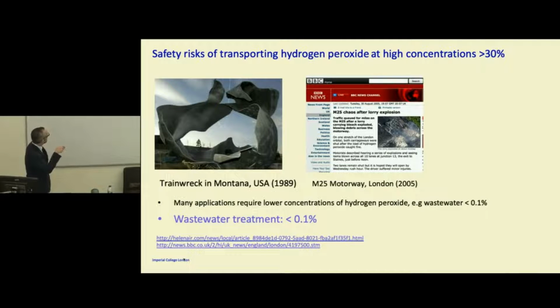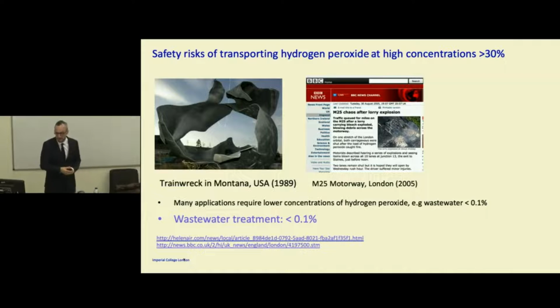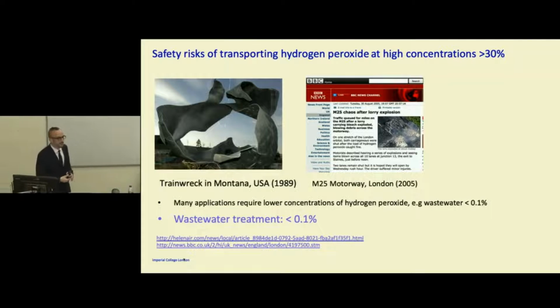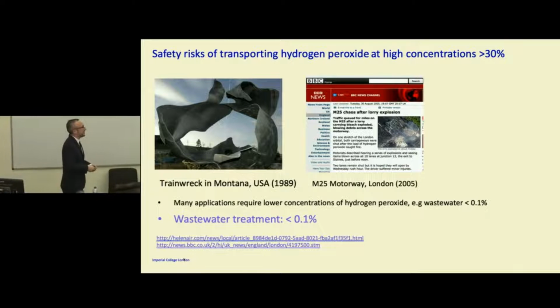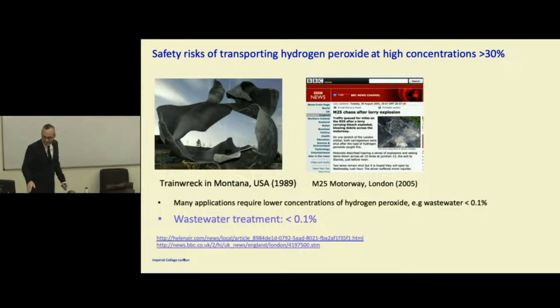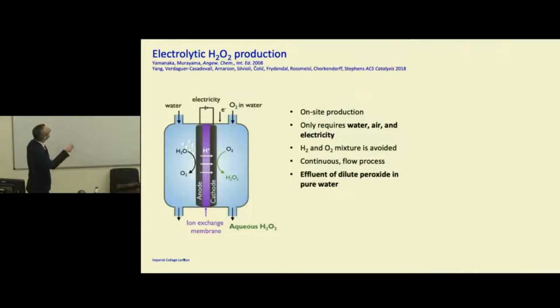So usually, if you're trying to clean water, you only need a really, really low amount of hydrogen peroxide, around 0.1%. So we started talking to people in industry and said it'd be great if you could actually use electrochemistry for making hydrogen peroxide. We said, well, actually you can. We didn't really understand why people were not trying to do it. So essentially all you need is water and oxygen and electricity, and then you can get dilute peroxide in pure water.